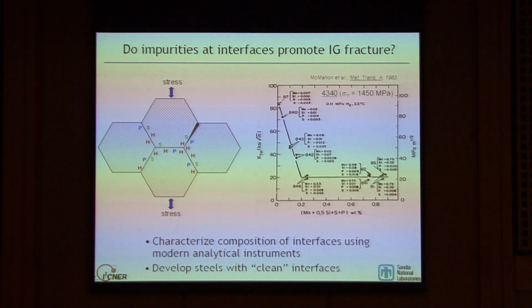Another possibility we need to consider: are there chemical impurities or alloy impurities in these steels that segregate to the grain boundaries and enable intergranular fracture? It's widely accepted that impurities such as phosphorus and sulfur in steels can segregate to grain boundaries and enable intergranular fracture, particularly in the presence of hydrogen. The phosphorus, sulfur, and hydrogen could all be acting to weaken the bonds at these grain boundaries and allow cracks to propagate along them.